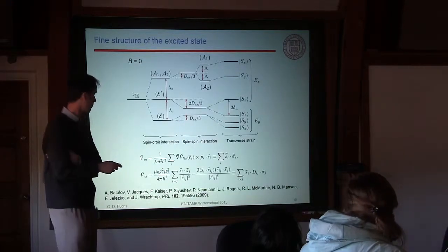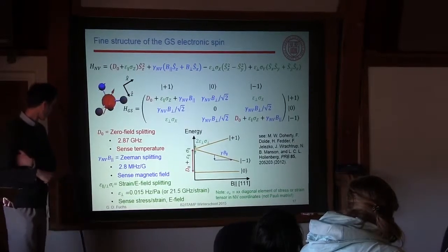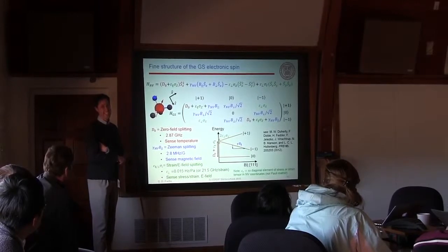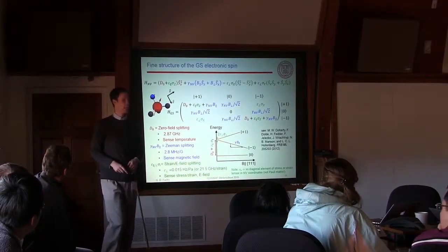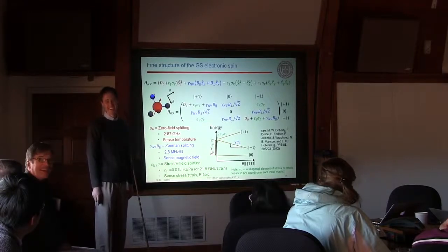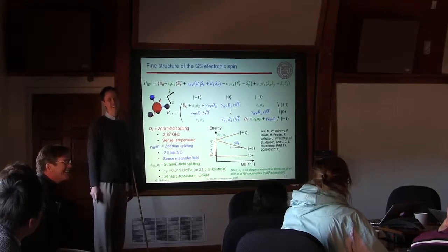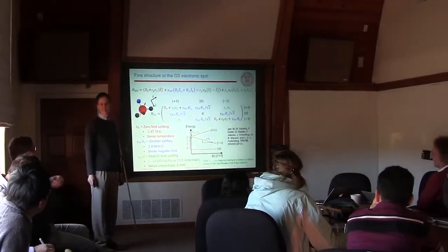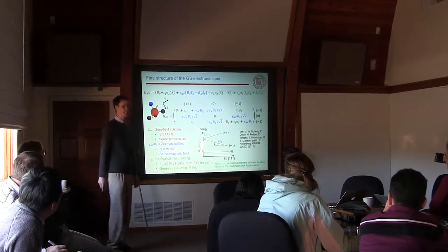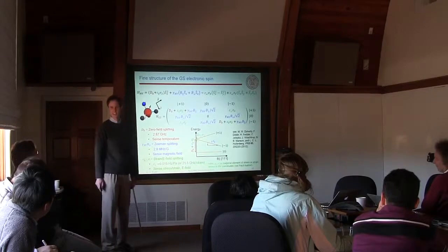So, if I look at the number just behind you, it seems to be a fraction of a hertz. Yeah, it's teeny. So do you need to worry about it at all? It's the whole basis for my group's experiments. The answer is yes. A pascal is a very small pressure. Yeah, for a diamond, though, we can put in tens of megapascals of stress. So then it ends up being big megahertz.